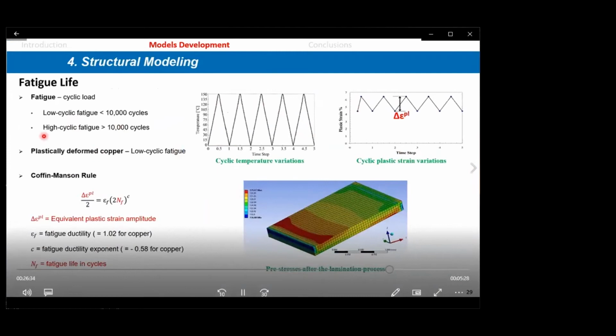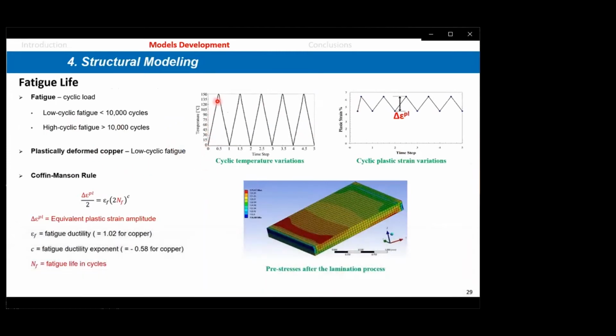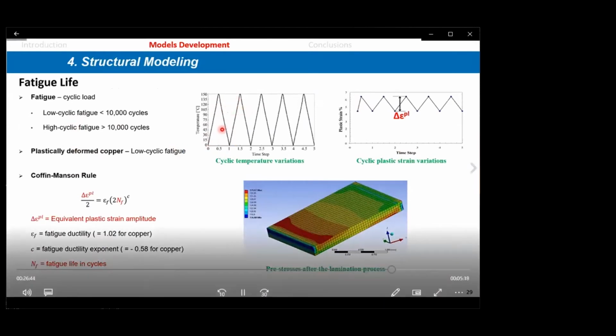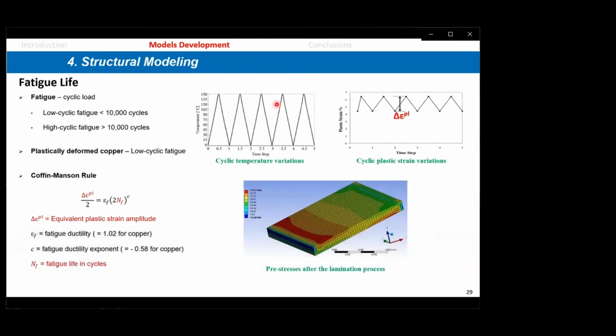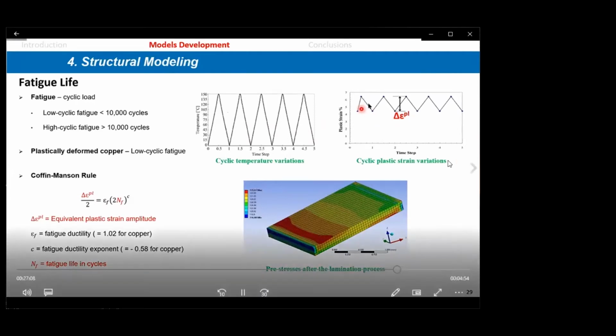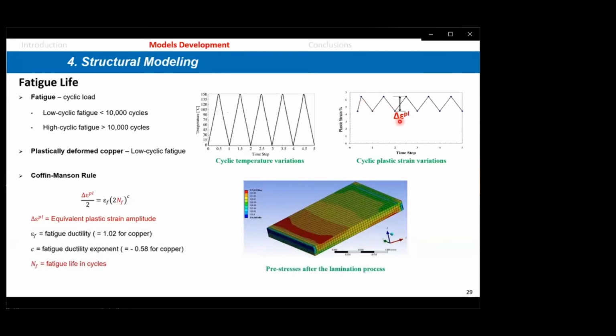Now, to analyze fatigue, of course, our panel, or the ribbon, because we are looking into the ribbon in more detail, is subject to a cyclic temperature over time. So how to simulate this cyclic temperature variation, heating and cooling? We just take one day, and then we repeat it many times, in terms of the variation of temperature in that day. From this, we calculate the stresses and also the strains, and particularly the plastic strains, and particularly the amplitude of the plastic strains. So everything is cyclic, and in particular plastic strains are cyclic, and we are interested in amplitude. Why are we interested in amplitude?